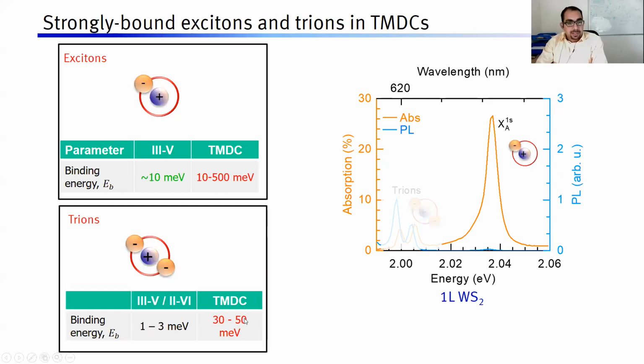And then we also know that the trions in these materials are also strongly bound. They have binding energies of the order of 30 to 50 meV, and they appear as peaks below the exciton by 30 to 50 meV. So they are also visible at much elevated temperatures compared to the III-V semiconductors. Here, the blue curve is the luminescence, light emission spectrum, and this orange curve is the absorption spectrum. You can see two types of trions. We will see the reason why there are two types of trions in this semiconductor. These two types of trions appear both in absorption and luminescence as equally well separated lines.